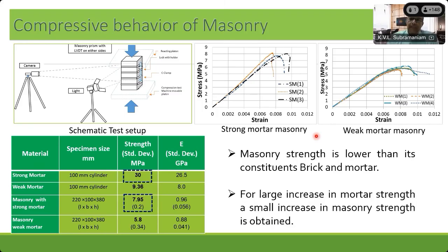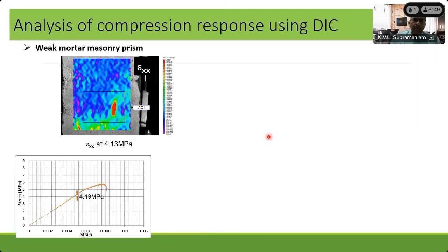Now, the other thing that we notice is that for a very large increase in mortar strength, that is when I went from weak to strong mortar, the strength of the mortar actually tripled. It went from 10 megapascal to 30 megapascal. The masonry strength that increased when going from weak to strong mortar in masonry was very small. So there's only a very small gain to be achieved in using a strong mortar when you're dealing with a very soft brick.